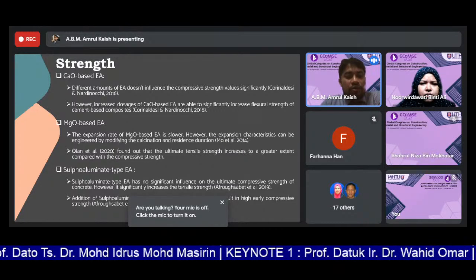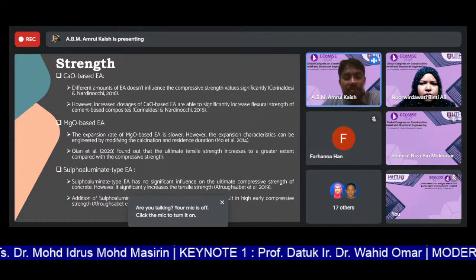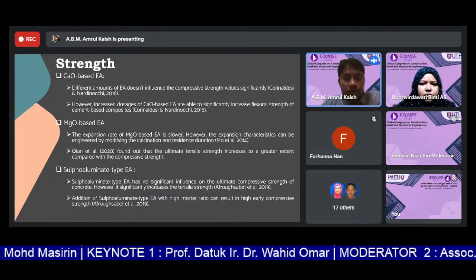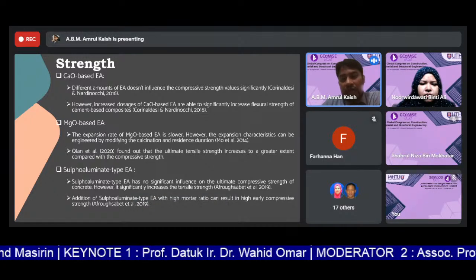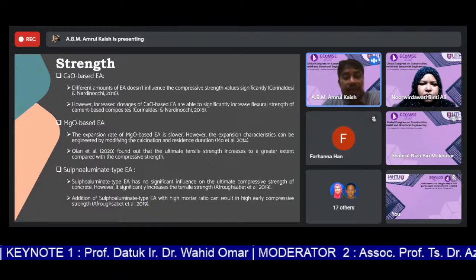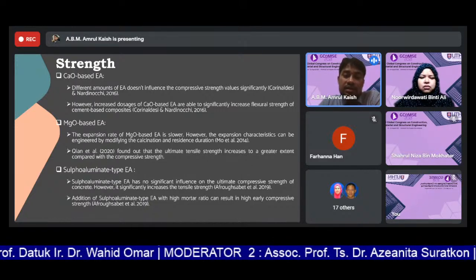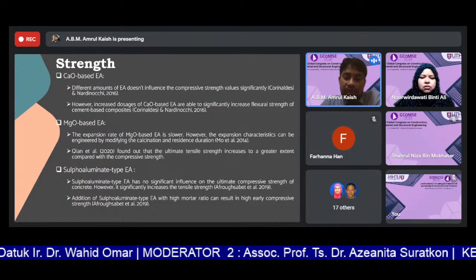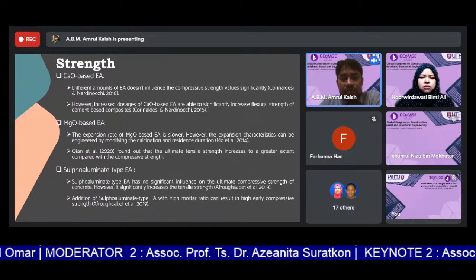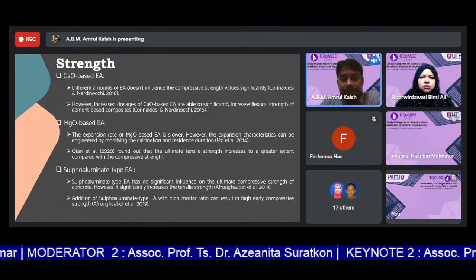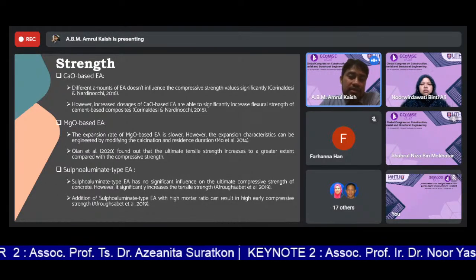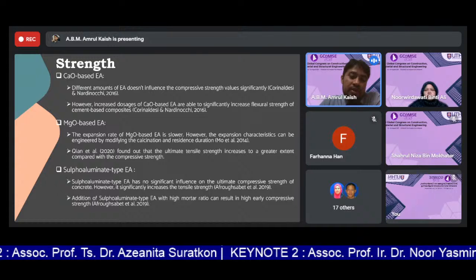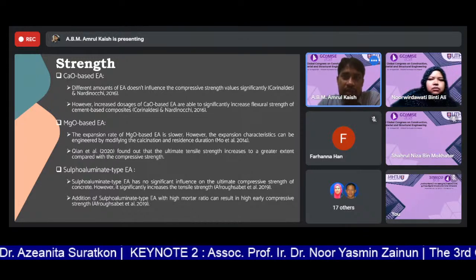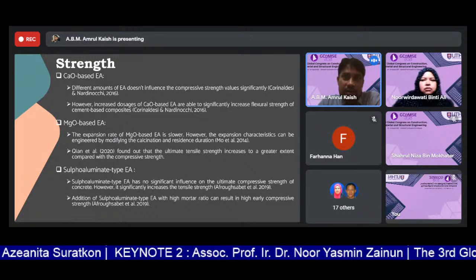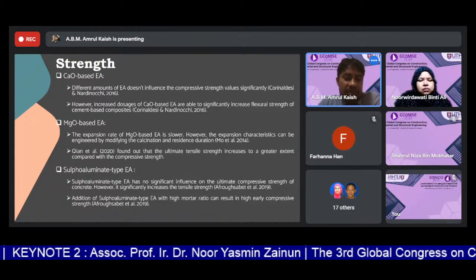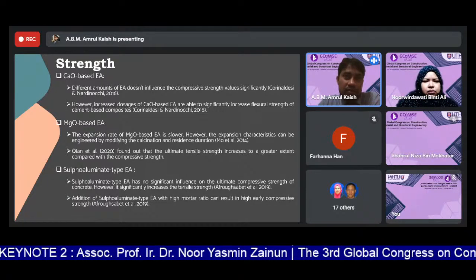Then magnesium oxide based EA, the expansion rate of the magnesium oxide based EA is actually slower. However, the expansion characteristics can be engineered by modifying the calcination and residence duration. And another study found that the ultimate tensile strength increased more than the compressive strength. This is also due to the partial pre-stressing effect of the expansion of the microfibers.